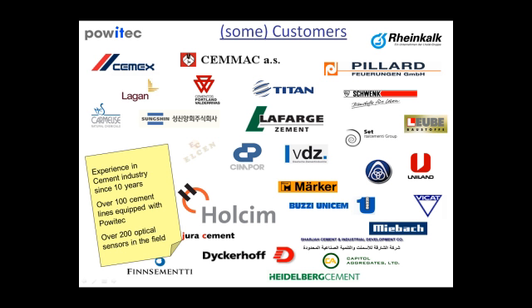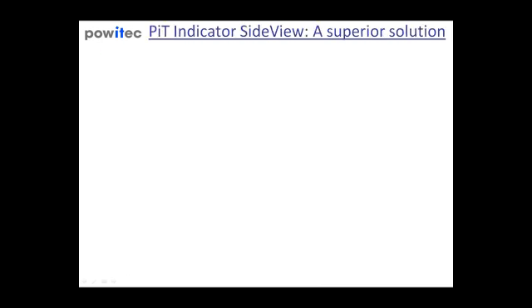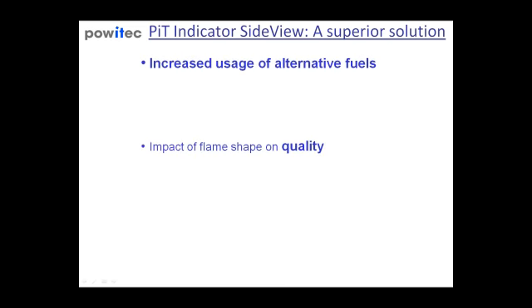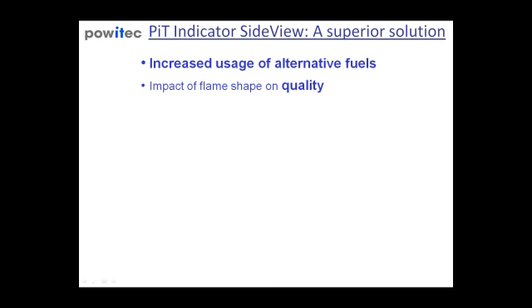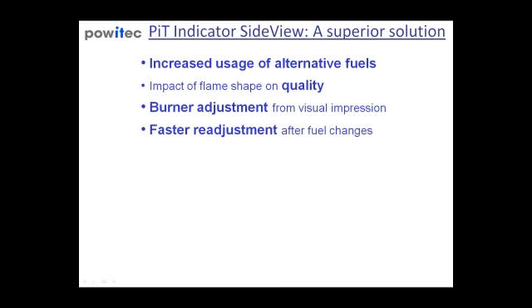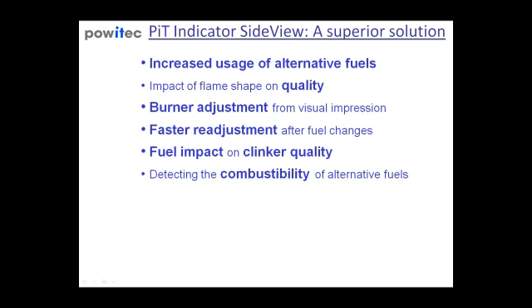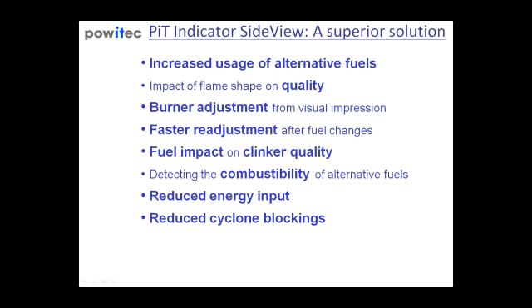Let me summarize why Powitec says that the PiT indicator SideView is a superior solution. You can increase the usage of alternative fuels, and you can see the impact of flame shapes on the quality. You can allow the operators to do burner adjustments from their visual impression to use the burner as a very effective quality actuator. Process experts can do a faster readjustment after fuel changes, and you can see the fuel impact on the clinker quality. The polylines clearly show the combustibility of alternative fuels, and with this instrument you can reduce your energy input. You can reduce your cyclone blockings, reduce the refractory wear, and also prolong the lifetime of the burner tip.